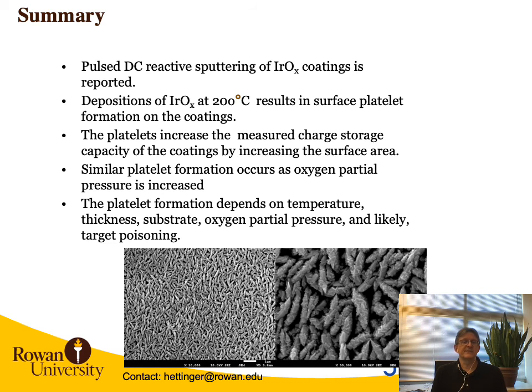We presented the synthesis of iridium oxide by pulse DC reactive sputtering. At 200 degrees C, we saw these interesting surface platelets, which led to improved performance. At high oxygen partial pressures, we saw similar platelets, which also led to high performance. All of these are likely higher performing due to increased surface area. The platelet formation depends on temperature, thickness, substrate, oxygen partial pressure, and likely target poisoning, because we have some pretty high oxygen partial pressures. The thickness dependence comes in because you need to have a certain thickness before you can start nucleating the platelets, and we've provided significant evidence for that.